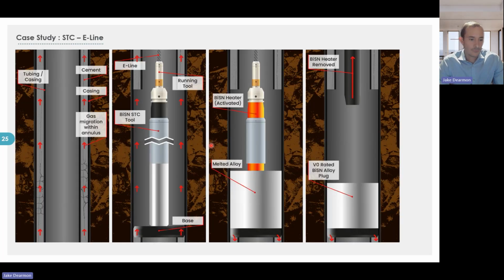I'll go through some of the storyboard here. So obviously, we start with a well that has sustained casing pressure and compromised cement going up the backside. Our typical operation would be going in and section milling anywhere from a 5 to 8 meter window. So a little bit better than a 30 meter that you would for cement, but we would section mill that 5 to 8, 9 meter window.